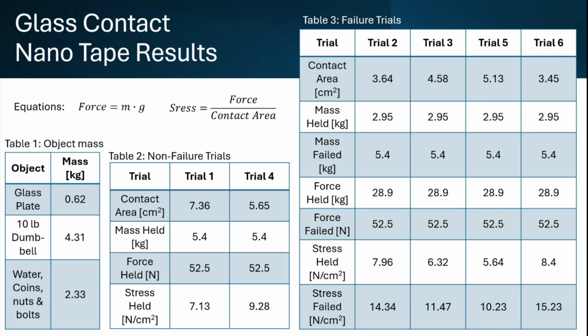You can see that in trial 5, which was the lowest, stress failed was 10.2, and this is just a little bit higher than the maximum non-failure trial, which is 9.28. So these are really the values that are important. So the maximum stress is probably somewhere between 9.28 and 10.23.